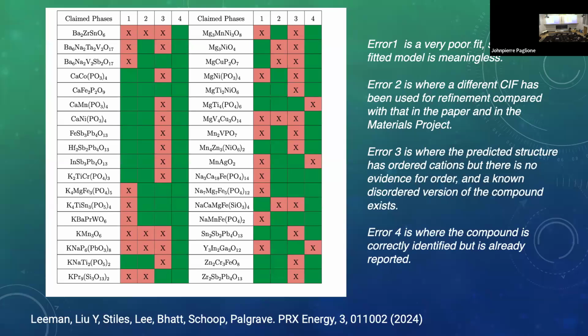And so you see one of these errors is present everywhere except this one compound right here. This compound was, by the way, reported while this paper was in review, so they were too slow to actually get there. But to be fair, I can give them that one compound that they correctly identified. It's easier to say something is correctly identified if you know that the material exists, because then it's easier to fingerprint powder X-ray patterns. You have less burden of proof than if you claim a new material.